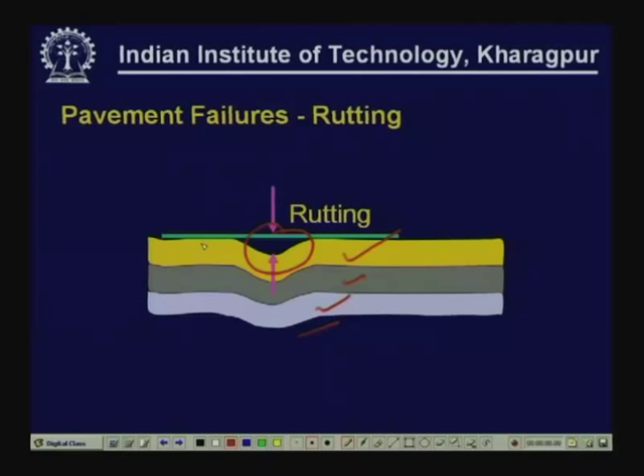Many recently constructed pavements with thick bituminous layers have shown this rutting problem. On investigation, it was revealed that the problem was mainly confined to the thick bituminous layers used, rather than arising from subgrade, subbase, or base issues. What we see at the top is an accumulation of all permanent deformation occurring in different layers. In designing mixes, we aim to ensure that mixes do not undergo excessive permanent deformation during their service life.